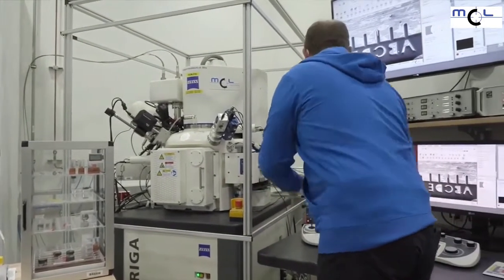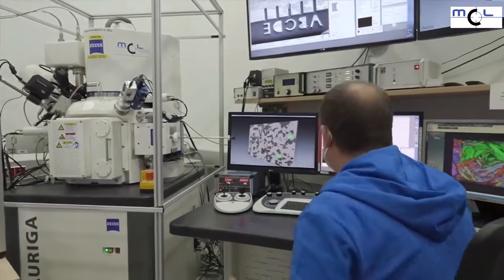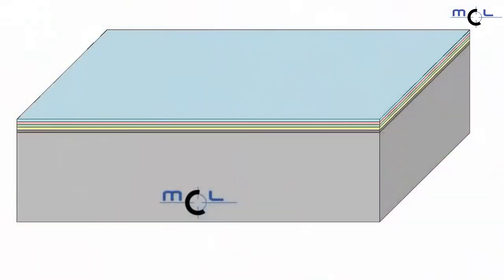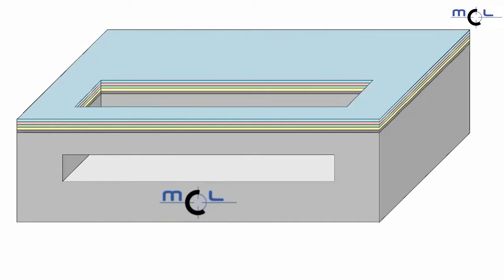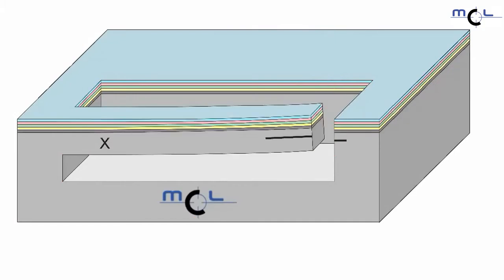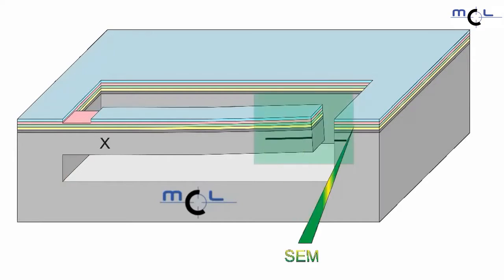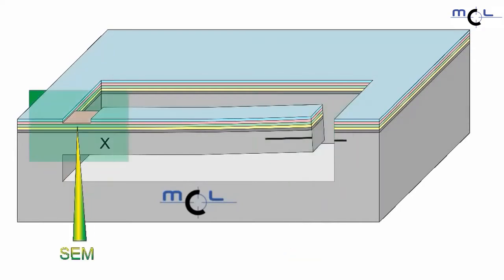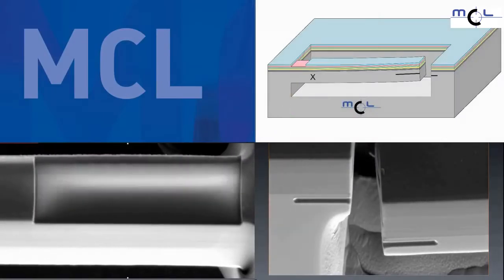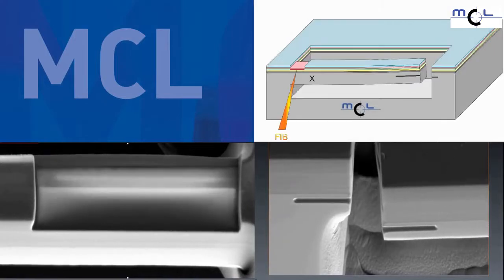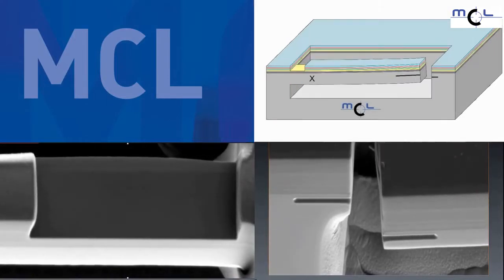For the mechanical characterization of the multi-layer system, we use the ion beam layer removal method. Within this method, a micro cantilever is cut. Then around 10 nanometer thin slices are removed from the cantilever. With these material slices, the residual stress is also removed, and from the change of the cantilever deflection, the residual stress can be reconstructed.